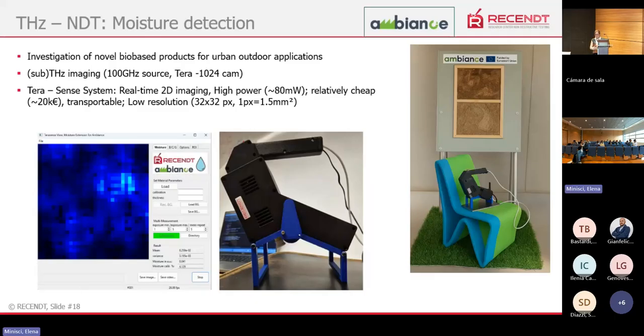And afterwards I will show a small demo with this moisture detection sensor, which was developed in the AMBIANCE project for detecting moisture in panels which also sit outside. Therefore we use a sub-terahertz source to illuminate the samples. It can be all kinds of bio-based samples if you calibrate the sensor for them. The reflected signal we get is summed up over the 2D image to make the mean, and we can calculate back to the moisture in the sample.